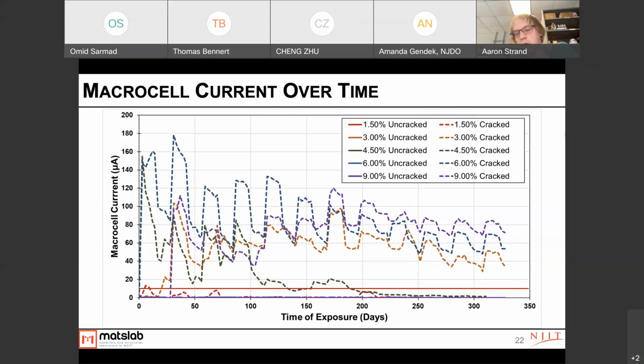And as we got on in testing, we do see that stabilize with the 9%, 6%, and the 3% all in a line with each other in the level of macrocell current. The testing was stopped just shy of 1 year, and this was due to the testing corresponding at that point with the pandemic, where our lab had to shut down, and it didn't make any sense to restart the testing, because the ponding cycling is what enabled the progressive chloride ingress into the specimens.